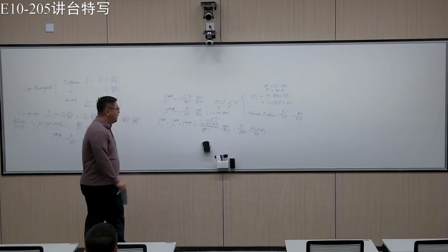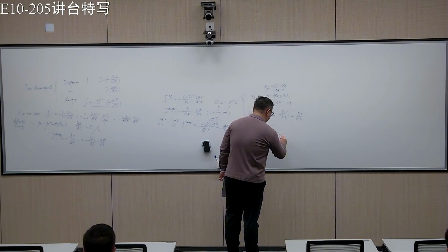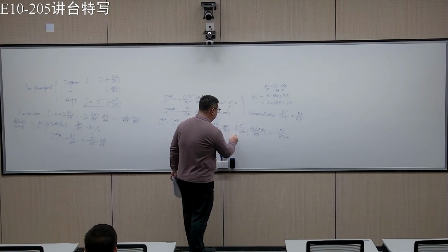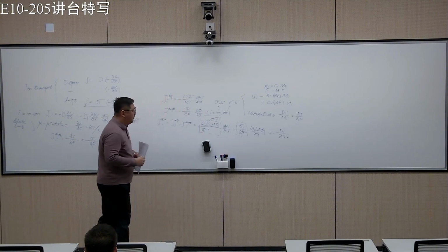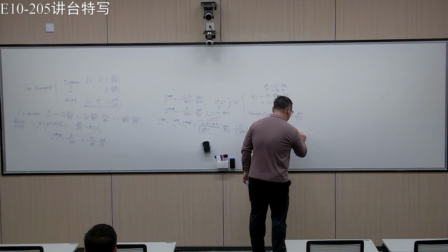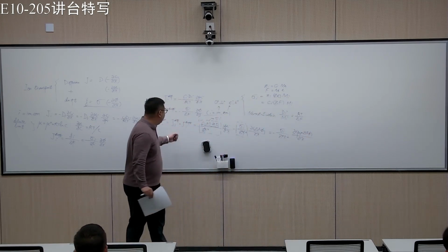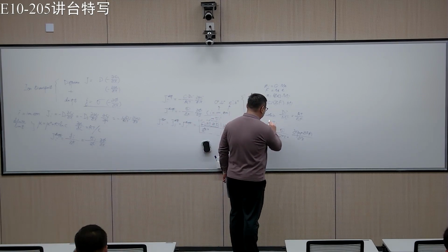So then we have this very nice form: Zi squared F squared sigma i. This is basically the common part. Then what's left is the driving force, partial x. So you can see that this is basically the Ji.